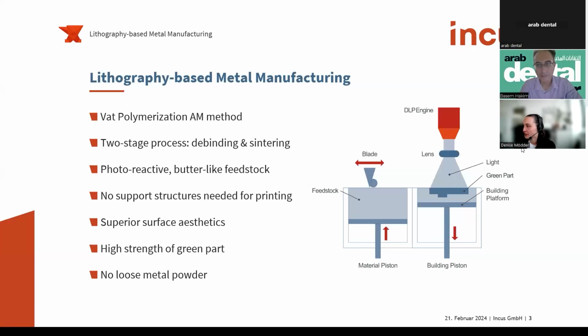Lithography-based metal manufacturing has it already in the name. We have a vat-based method, so a light-based method, polymerizing actually a slurry that contains the metal powder. So everything is homogeneously mixed inside this slurry. The slurry is more wax-like, so it's solid at room temperature, and it's liquefied by a blade. We will see a video in the next slide. So after the printing process, we still have to undergo a debinding and sintering to remove all the binder content of the parts, and the sintering to really densify the metal particles that we mixed in.